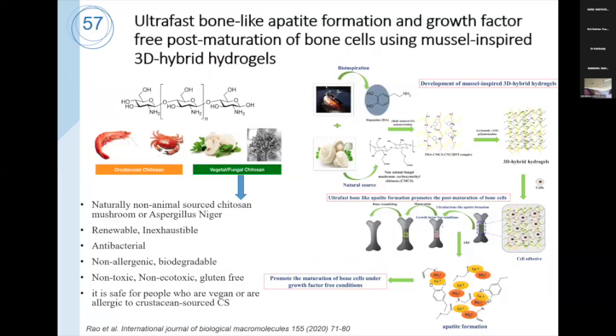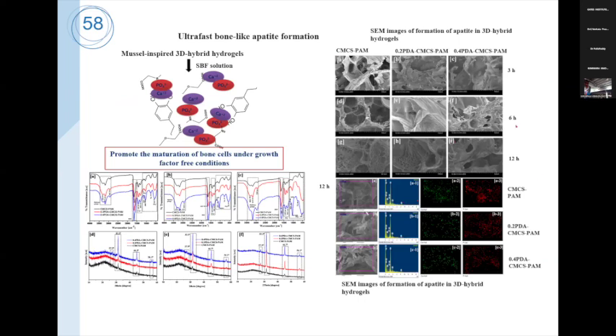So we use dopamine. We use the dopamine compound in order to accelerate the ultra fast bone-like apatite formation within the scaffold. We have used natural polymers like carboxymethyl chitosan from fungal mushroom, and we combine it with dopamine and then prepare the 3D hybrid hydrogels. We use mesenchymal stem cells, to see how the cells grow and differentiate to produce functional tissue. In general, growth factors are necessary, but in our case, without growth factors, the hydrogels can promote the maturation of bone cells under growth factor free conditions, because these hydrogels can biomineralize within 12 hours.